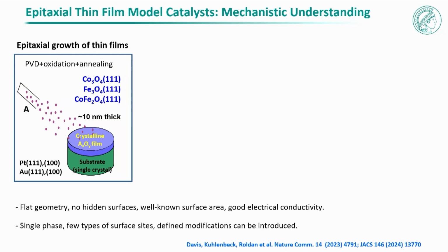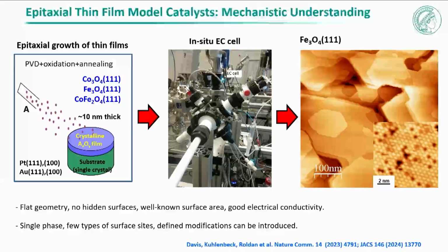To be able to get more understanding, some of these systems are very complex. I mentioned before we are working with inorganic materials, but when you are working with a nanoparticle, you need to consider the effect of the particle size, the shape, and the changes of these structures, the surface composition. So sometimes it's good to start with thin films, because if you make these thin films, you can control, for example, the surface termination. And we can make these thin films with different orientations. You can also control the initial composition.